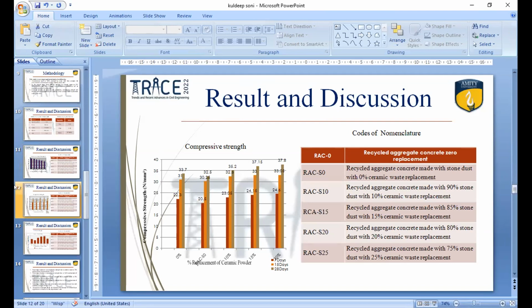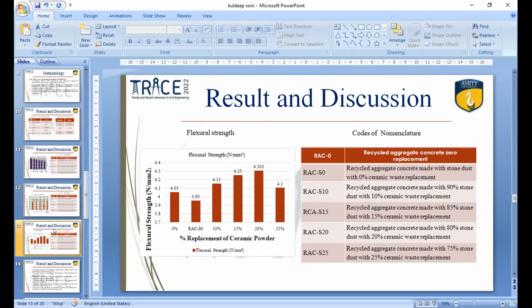Replacement of stone dust by ceramic waste leads to an increment in the compressive strength up to the optimum replacement value of 20%. At the point of optimum replacement of stone dust with ceramic waste, compressive strength is increased by a maximum of 16.3%. But the workability of the concrete decreases with the increment of ceramic waste in the concrete. The workability of the concrete lies between 20 to 50 mm.